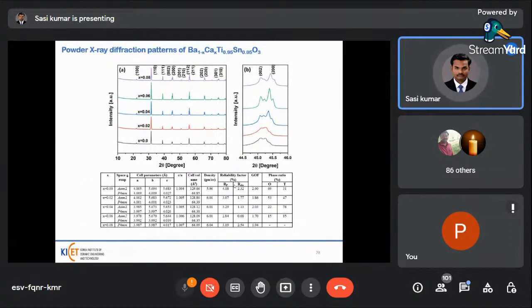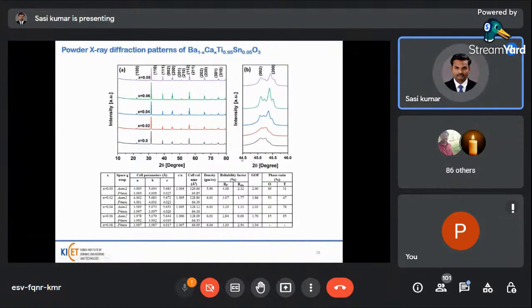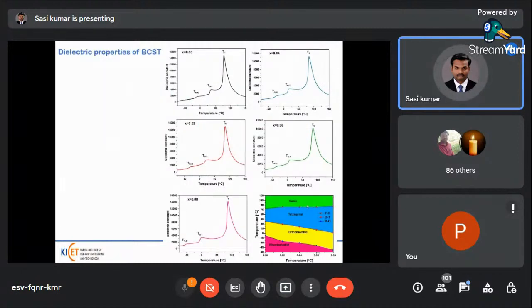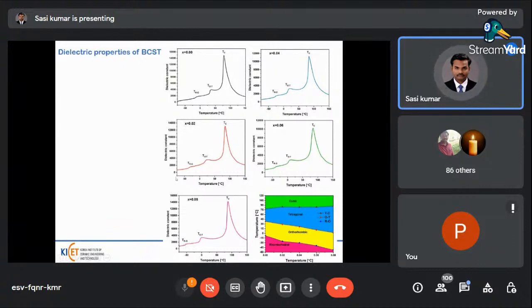And then another lead-free ceramic is calcium doped barium Ti 0.95 Sn 0.05 based materials. And here this is the powder x-ray diffraction and cell parameters of different structures, and the phase ratio of these materials is refined using the Rietveld refinement. And then dielectric spectra: the BCST material dielectric properties were measured at low temperature from minus 75 to 150 degrees Celsius.